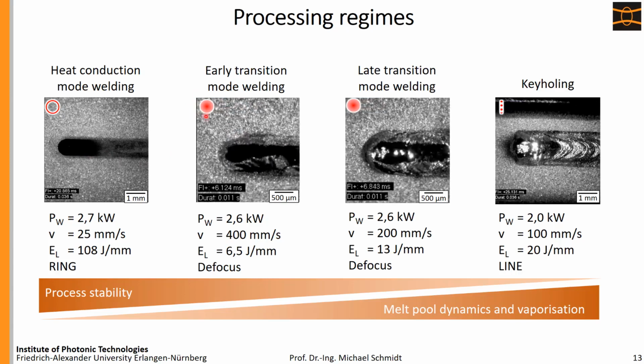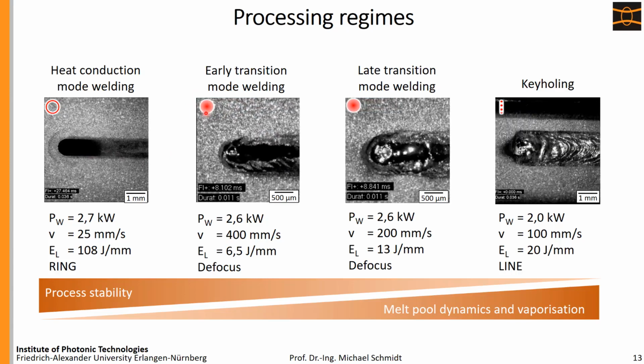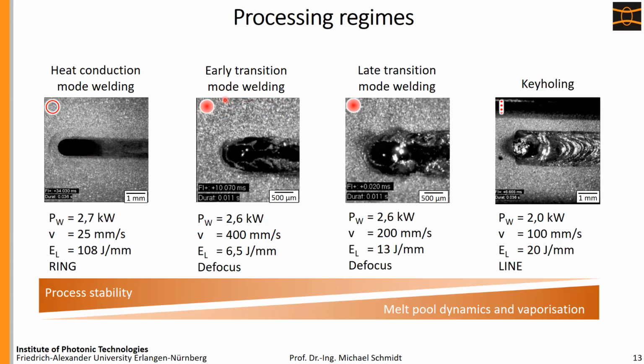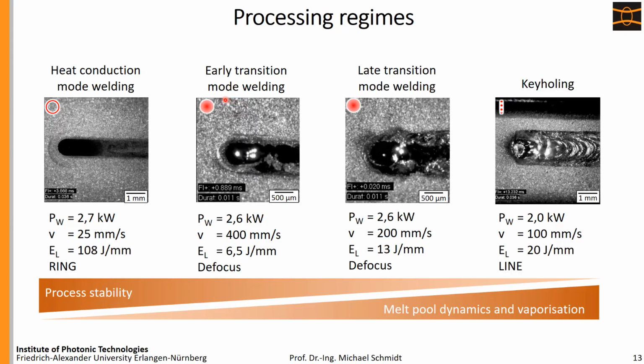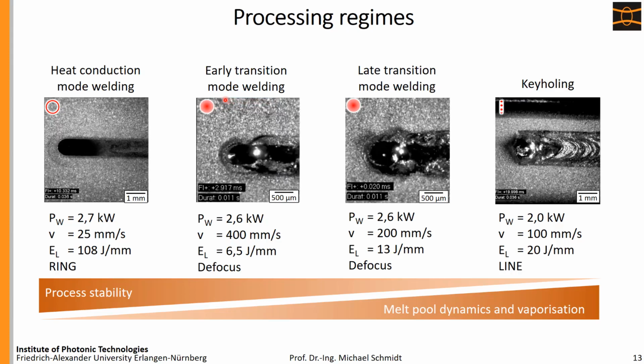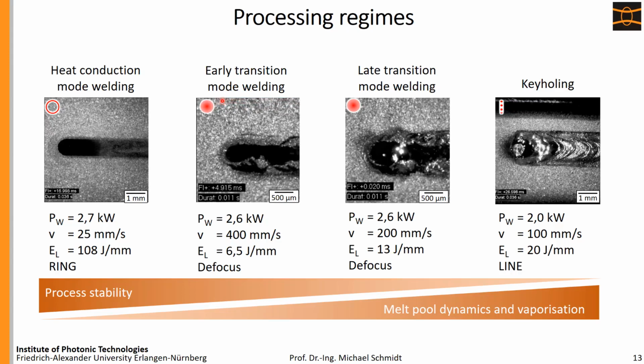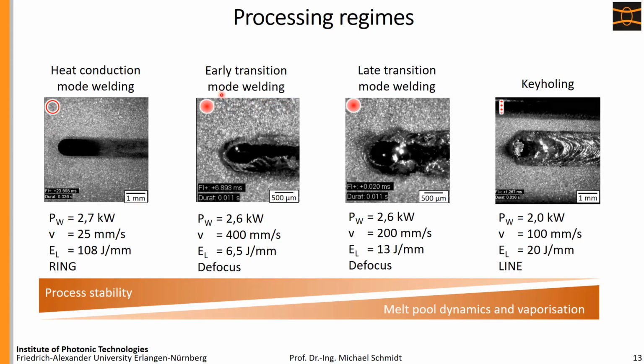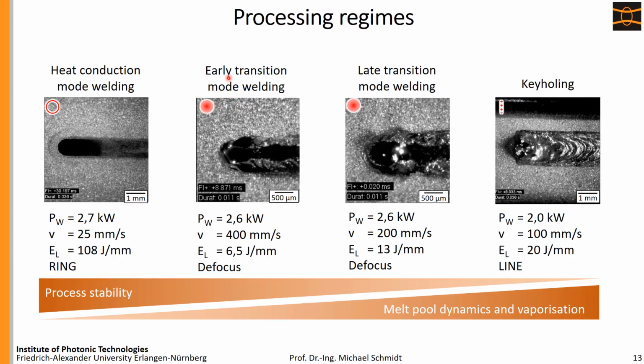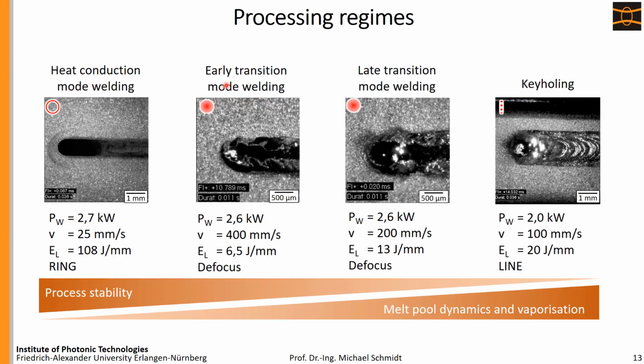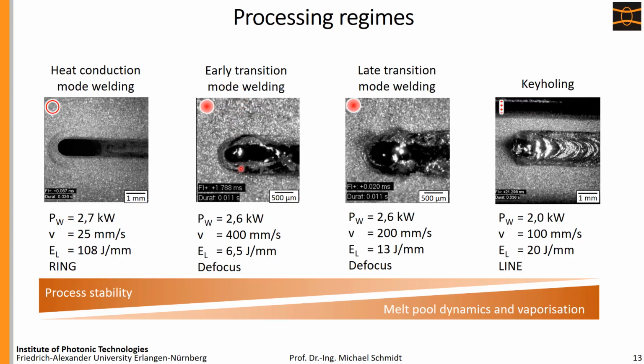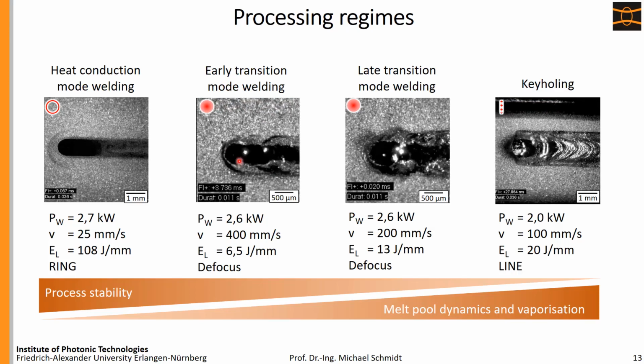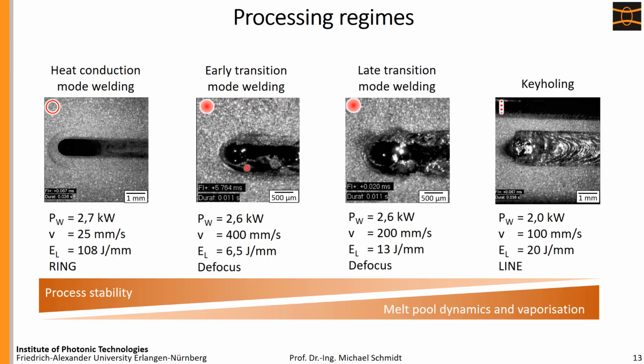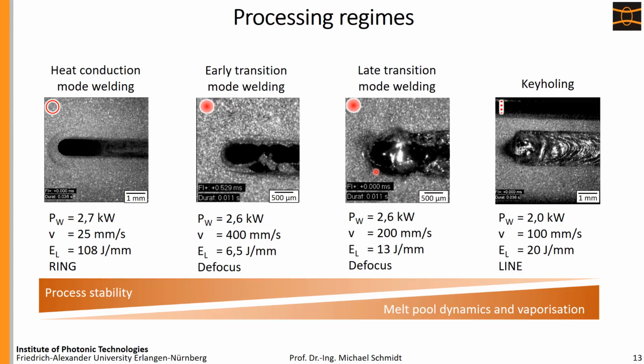Here we use the defocus, but with process parameters that are in between heat conduction mode and deep penetration mode welding. So this is what we call transition mode. Of course, we do not want to go into keyhole welding. And this is the early phase of the transition, so we are nearer to the heat conduction. And you can see there's some significant waves running back, and there is some higher process dynamics that you can see here. So I have to restart.